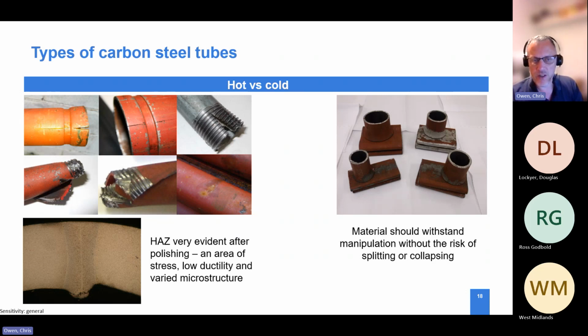There's a variation in mechanical properties across there, as well as the problems associated with ductility, which then means that if these tubes are work hardened, or the weld quality is not good, or the steel is not as good as it should be, then you can see a lot of splitting, tearing of threads, for example, or collapsing of the actual tube itself. What we try to do in the hot finish process is remove all those stresses and eliminate the heat affected zone.